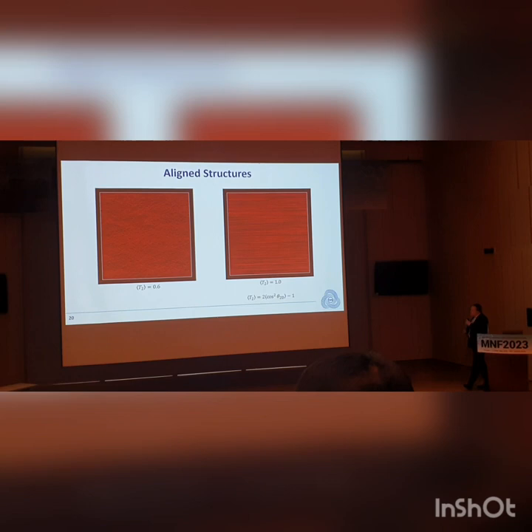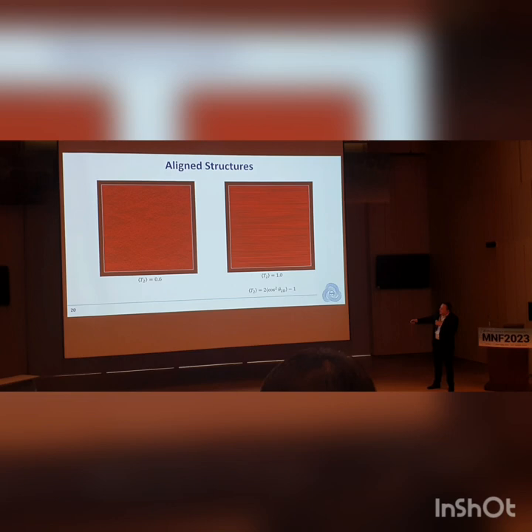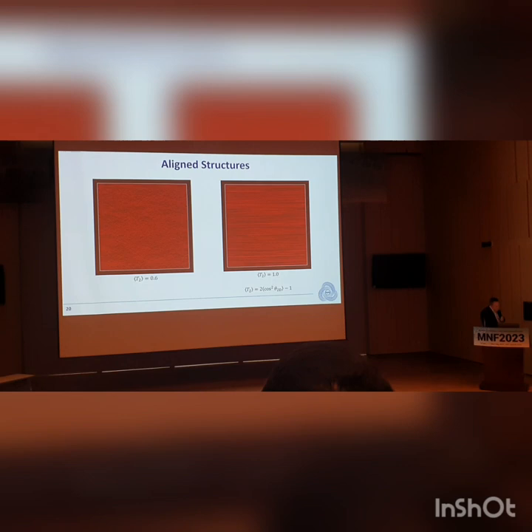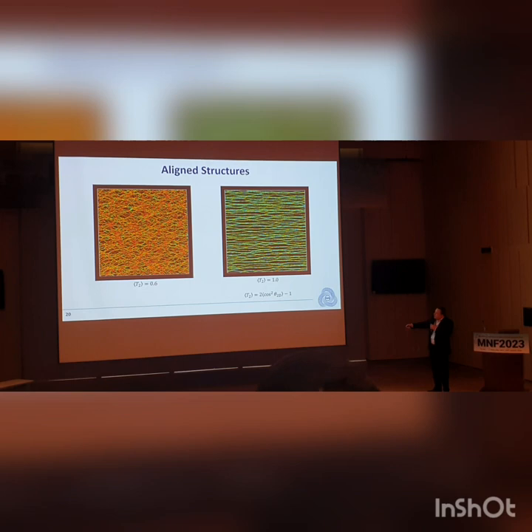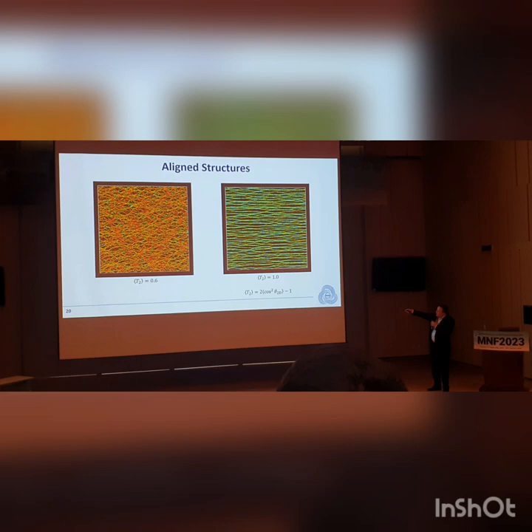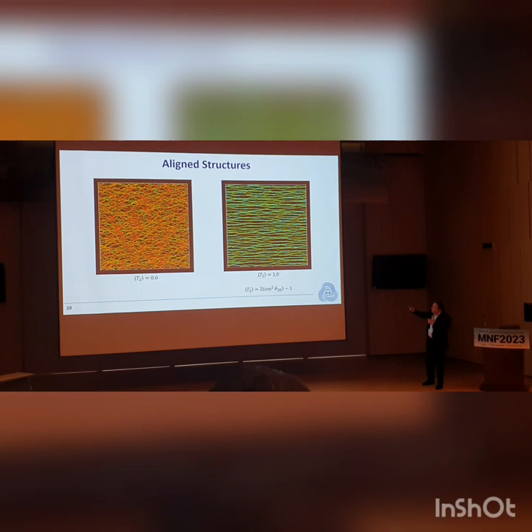Now applying alignment: with a moderately aligned structure at t2 = 0.6 (maximum is 1, meaning fully aligned in the horizontal direction), we let tubes aggregate and observe a dramatic difference compared to unaligned structures. For low degrees of orientation we see moderate bundling with many junctions and misaligned tubes. At high orientation we get almost complete bundling with very intermittent junction points and large void regions between them. So the effects of alignment are not just about tube positioning — alignment also affects bundle structure.